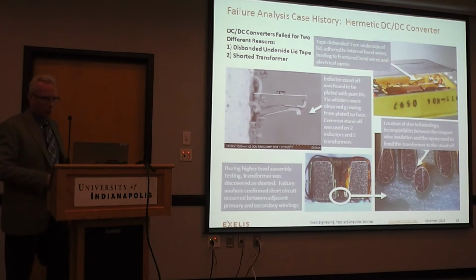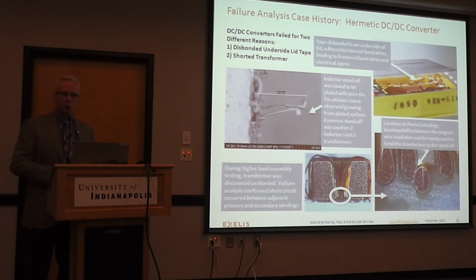Well, it turns out this did not take less than, I would say, a week to determine, because this involved research on a number of materials. There is a potting material that's used to bond the transformer to the standoff. That potting material was incompatible with the magnet wire insulation. So essentially it softened, dissolved, affected the physical properties of that wire insulation. And so, unbeknownst to the manufacturer of this module, they had used an incompatible material. So that was the next why.